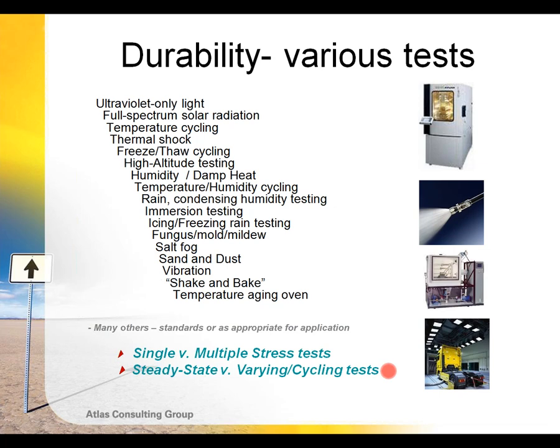And so if you test all different ways, all factors or most conceivable factors, even though some of those could be proven not to have much of an effect or any effect, you've spent a lot of money on testing, and have developed a very complicated test. And then, more importantly, if the product does change in properties or performance or fails outright in a multiple stress test, it becomes very difficult to deconvolute, or to go back and identify, which specific stress or combination of stresses caused the failure of the product, because you have too many experimental variables all going on at the same time. So that is one of the reasons that we typically use a phased approach. Identify which stresses, perhaps through some pre-screening testing, are likely to affect the product.